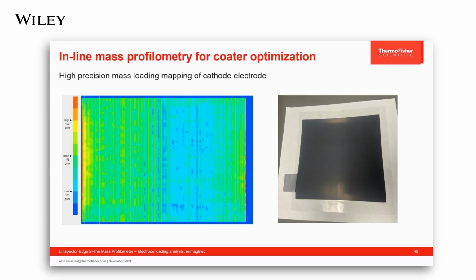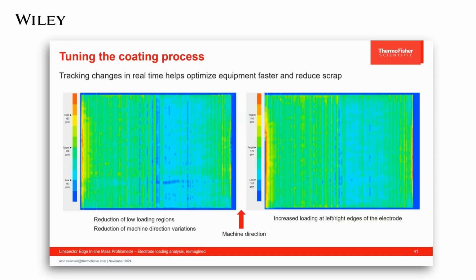You can also see small vertical streaks that are actually visible in the photo of the same patch on the right. If you look closely at the light reflection on the top and the bottom center of the area, you can see these streaks represented as green and blue vertical lines on the mass profilometry data. This confirms that the measurement itself produces a real measure of mass loading variation on the patch, which can be confirmed by sight.